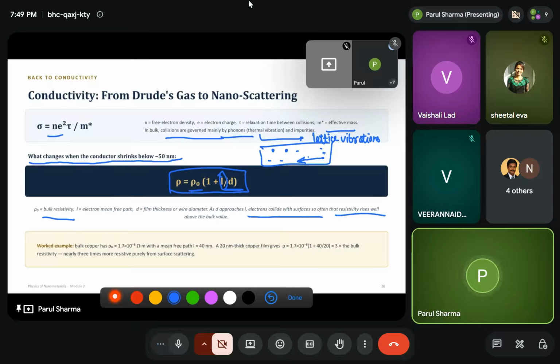So here we have an example: if bulk copper has this rho naught with this mean free path, then if we have 20 nanometer thick copper, it will give us this value. It means it is increasing 3 times. But what is the reason for that? It is because we are confining the electron motion, and because of the electron confinement, or quantum confinement, the surface scattering is increasing. If the surface scattering increases, resistance will increase, and that's why the resistivity will increase. So when we are moving from bulk to nano, there is a drastic change, and from this example we can see a change of 3 times.